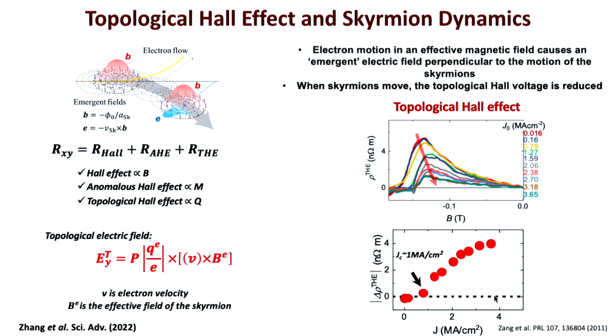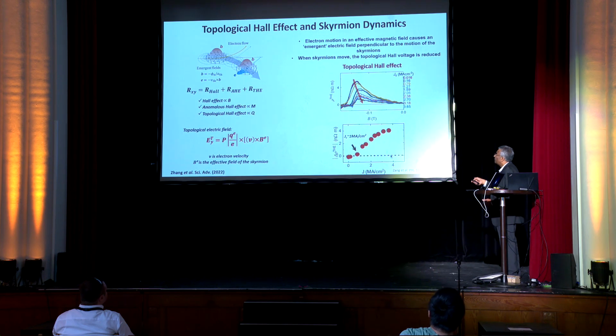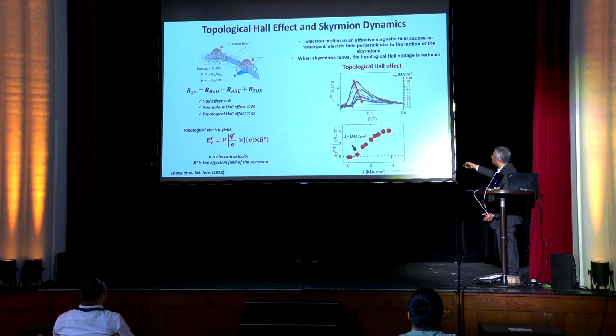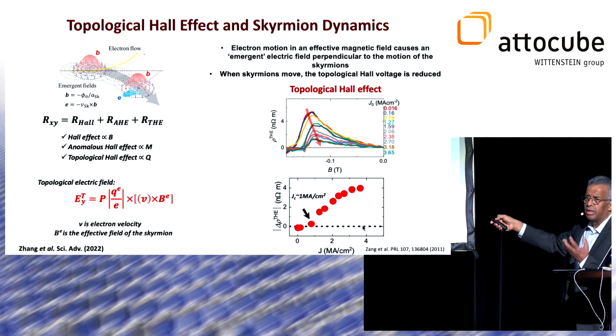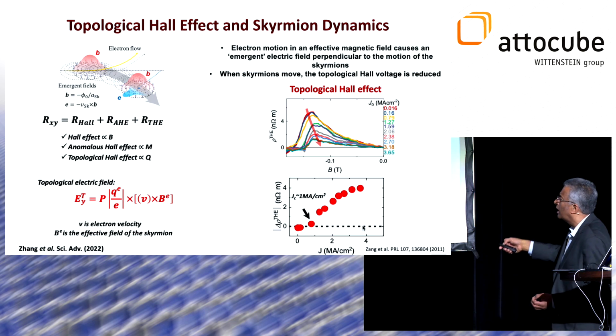And the motion of the electron through this skyrmion leads to a drift in one direction because of this emergent electric field. Now, as you apply a current to this, you can start to move the skyrmions, and you can start to see that the resistivity or the resistance contribution to the topological Hall effect keeps coming down. It's a very small value. It's not a huge value, so you have to really do it carefully.